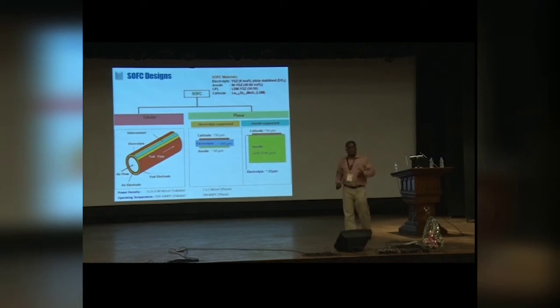So this as such can give you a single cell. But in this case, the electrolyte is very thin, so it needs some support. That support is provided by this porous anode. And about the porosity of anode and cathode, if you remember the last view graph, I said that these are porous and the electrolyte has to be fully dense. So the porosity should be 30 to 35%. That is essential, so that it allows air on the cathode side and hydrogen or any other fuel on the anode side to reach the electrolyte. So that is very, very important. The anode and cathode have to be porous, and the electrolyte has to be fully dense.